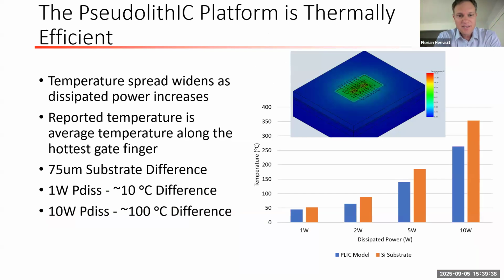And what you see is, if you look at temperature on the y-axis as a function of dissipated power, both for the pseudolithIC chip in blue and the GaN on silicon in orange, we achieve much lower junction temperature or peak temperature, up to 100 degrees C of difference when you dissipate only 10 watts across your chip, right? So very, very quickly, we are able to have better thermal performance.